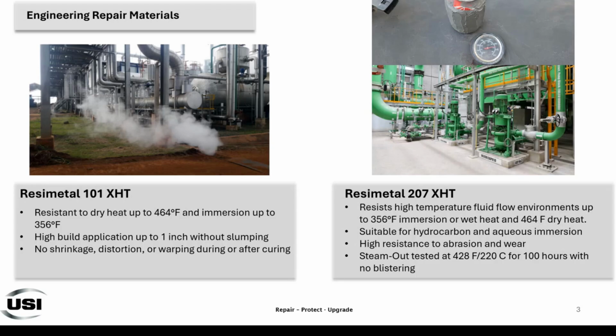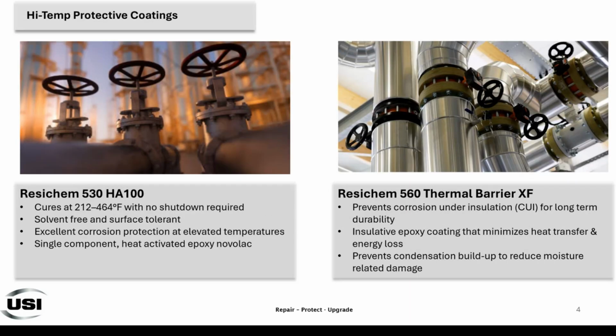This 101 should be coated with a finish coat like a Resimetal 205, 206, or 207. 207 XHT has a dry heat resistance up to 464 F and immersion temperature up to 356 and can also handle abrasion and erosion, suitable for hydrocarbons and aqueous solutions, and has been steam out tested at 428 degrees F or 220 C for 100 hours with no blistering. So you can see what kind of performance you can get from high temperature coatings.